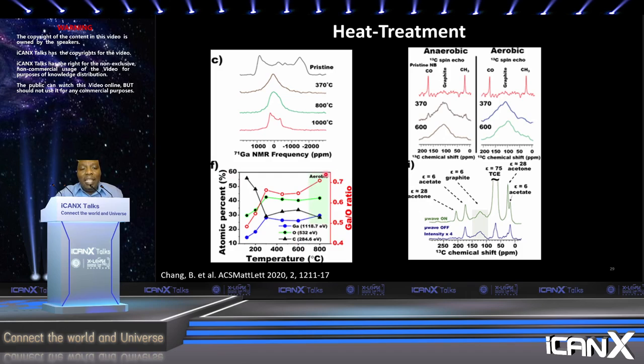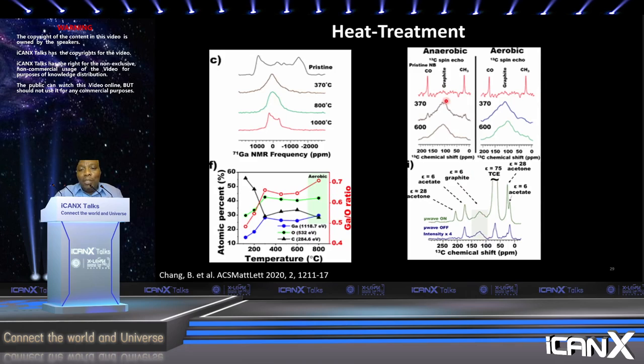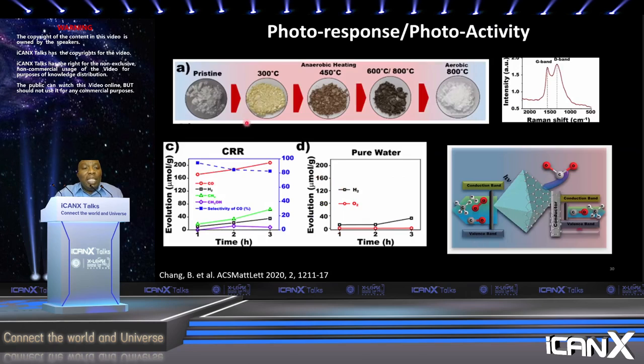And we see that in all cases, we are retaining some carbon. One of my colleagues had actually published a paper that says pyrolysis does not remove all the carbon, so we knew we would have some carbon there. And we confirmed that the carbon is graphitic by using solid state NMR. You see that carbon is only showing up when you burn your sample. It doesn't show up in the pristine sample. So we know that this is from the reduction of the ligands. And also we see it in the color. The pristine sample is white.